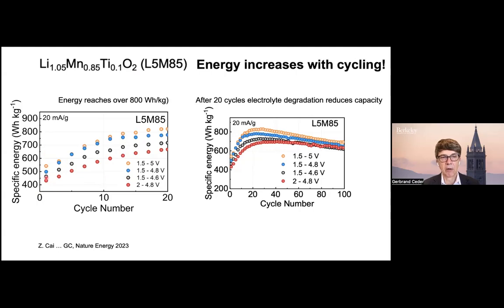And it starts from a relatively low number, so in the 400 to 500 watt-hours per kg range, going all the way up to 800 watt-hours per kg. I'm showing that here over longer term, you get this rise in capacity, and then you get this sort of slow decay. The slow decay is actually not materials decay, it's actually electrode issues. This is clearly established because of the small particle size in these milled materials, you get a loss of contact with the carbon, and you get EC breakdown, so the electrolyte breakdown, which builds up polarization. But I'll come to that issue.